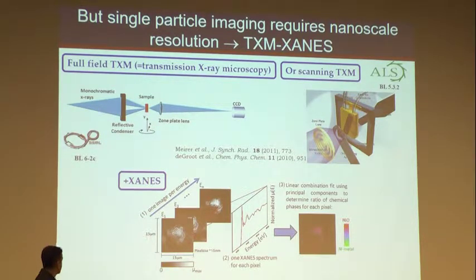And so in these particular measurements, you collect images at different energies, and then you integrate the intensity at each pixel for each energy to build a spectrum for each pixel. And then you reconstruct that spectrum. You can do a linear combination fit if you know the standards. You can do PCA analysis to extract components. Basically, you choose how sophisticated you want to get. And then you can build your map.